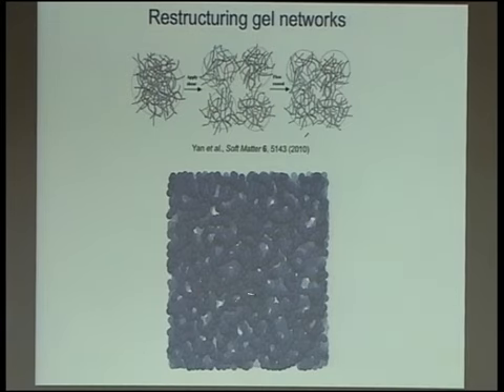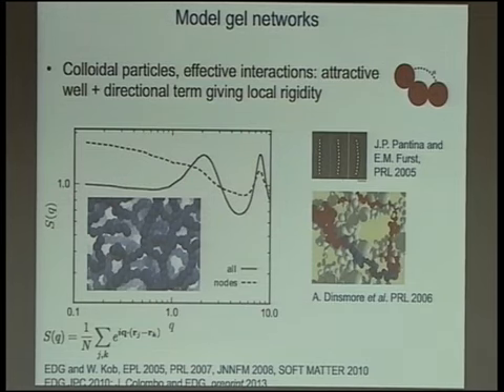And that forms, I don't know if you can see in the structure, basically a network of chains that interconnect in nodes. And it's not specifically related to one given colloidal system, but it reproduces a number of generic features of colloidal gel that can form in fairly dilute conditions, so at relatively low volume fraction. So basically what we do is that we have an effective potential between these particles, which consists of an attractive well, which mimics the attractive interaction between the particles, and to this we add an angular local rigidity between bonds that actually helps in stabilizing the type of structure that I told you.